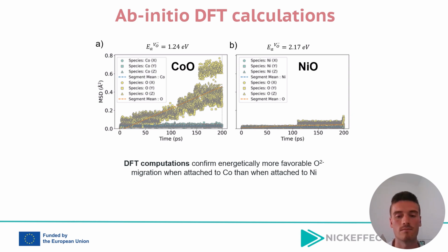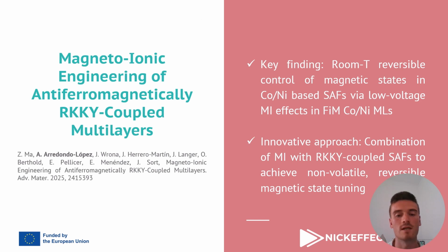Coming now to the second work, entitled Magneto-ionic Engineering of Antiferromagnetically RKKY Coupled Multilayers, the most important milestone was achieving room temperature control of magnetic states in cobalt-nickel-based shafts via low voltage magneto-ionic effects in ferromagnetically coupled multilayers, thanks to non-volatile, reversible, voltage-induced magnetic multistate level tuning.